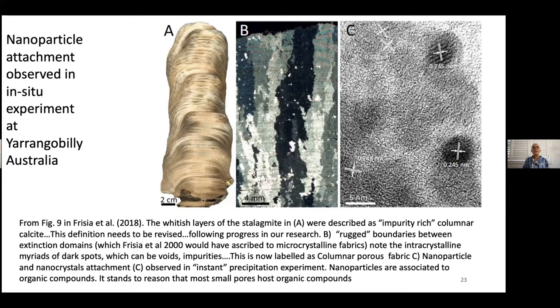How does it form? Now, from the drip water, again, it was one of my first experiments. It's published, in Frisia and others, 2018. In the water, I precipitated both nanocrystals and the crystal where you see the lattice. So this is a crystal portion, but then there are also the black dots, which are organics. So the crystal seems to be associated with some organic particulate that is around in the drip water. And then they start being attracted to each other and start to attach. So nanoparticles associated with organic compounds, the idea is, well, could it be that this kind of growth is what actually gives this fabric?